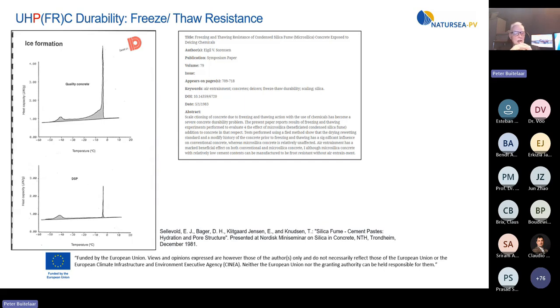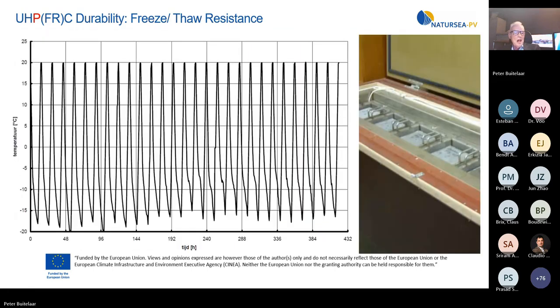We are using this when we are applying UHPC industrial floors in blast freezing in the food industry in special tunnels, where in less than 5 hours the temperature is going down to -40 degrees Celsius and going up again to 20 degrees Celsius plus. Research for the strengthening of orthotropic steel decks in 2002 confirmed that the 28 cycles from -20 to +20 degrees Celsius resulted in an average mass loss of 4 grams per square meter, compared to 100 times more mass loss of the reference 60 MPa concrete. Also, the adhesion of the thin bonded hybrid reinforced UHPC on the orthotropic steel decks was tested using the same 28 cycles. No delamination occurred.